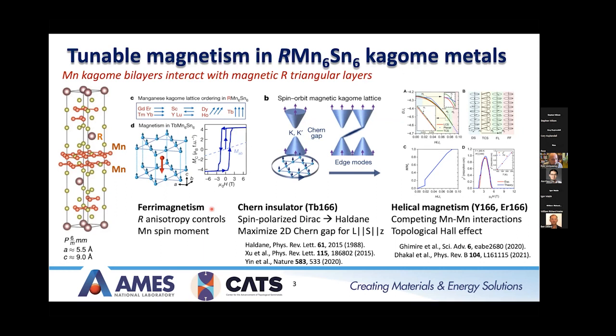I should say each layer, the rare earth and the kagome layers are ferromagnetically aligned, but the orientation between the rare earth and the manganese kagome layers is anti-ferromagnetic. So you have a ferrimagnetic structure, but you still get this net overall magnetization. And depending on the rare earth that you use, you get different anisotropies, and a lot of this depends on the crystal field splitting of the rare earth, as Lee Chin talked about earlier.